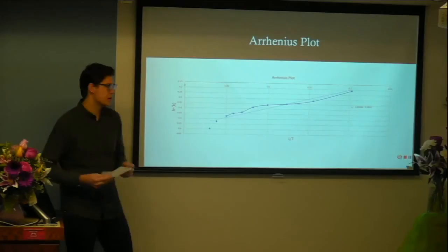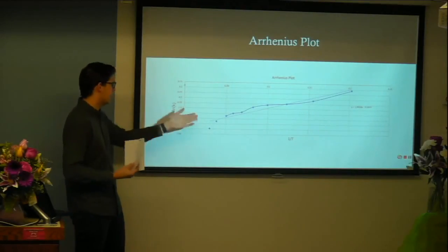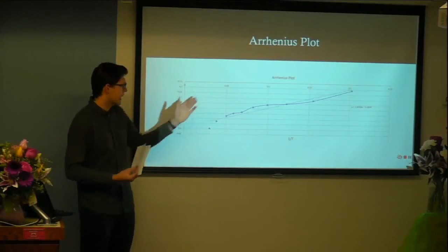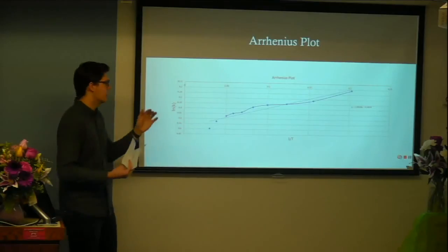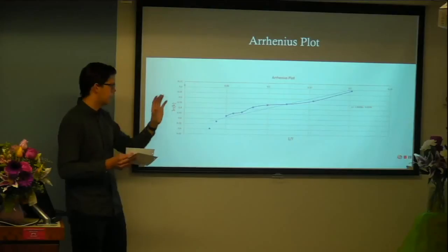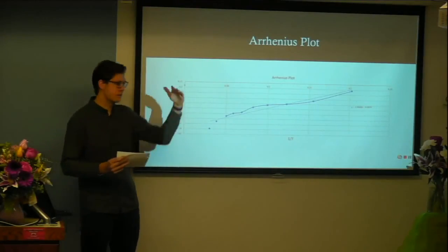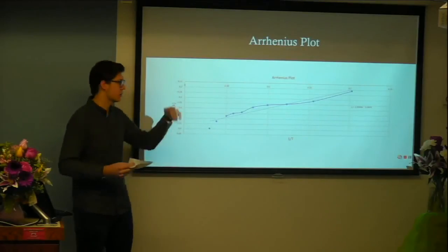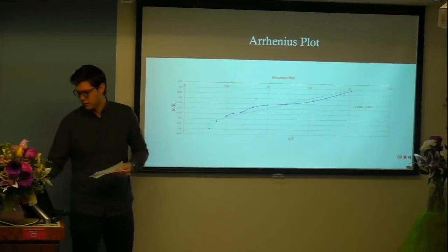And with this, the Arrhenius plot was made using the 1/temperature along with the rates that were gathered. Within this collection of data points, on the two extremes there was a lot of discrepancy in the data, whereas in the middle it leveled off and formed a nicer curve from which this plot was taken. And from here, the slope is where we get our activation energy.